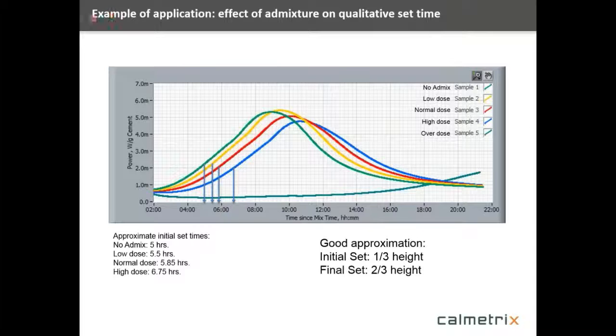All right, now let's talk about some typical applications. Here's a very simple one, but a very powerful example of how the instruments can be used. This is looking at the effect of admixture on the qualitative set time. Here we're looking at five different mixes, and the green curve is basically a sample with no admixture. Sample two is a low dose. Sample three is a normal dose of the admixture, and the blue sample is a high dose, and sample five has been overdosed. We're looking at the power here, so this was done on an isothermal instrument, though you could